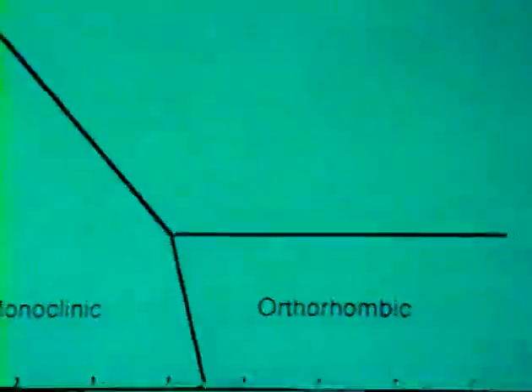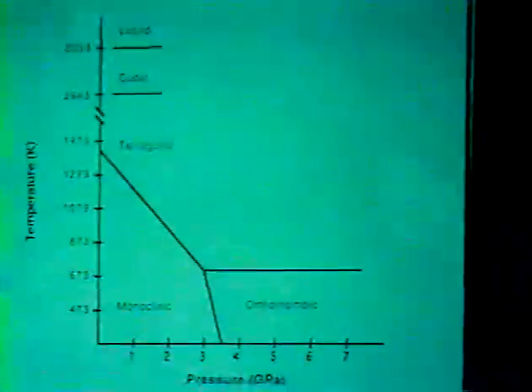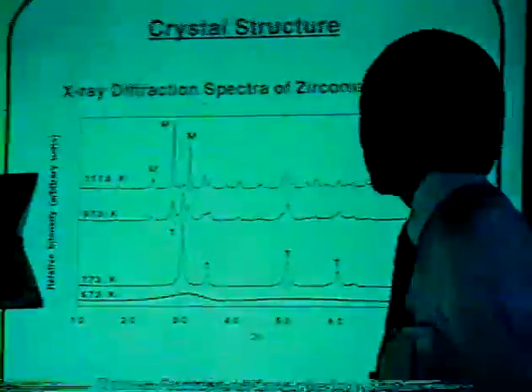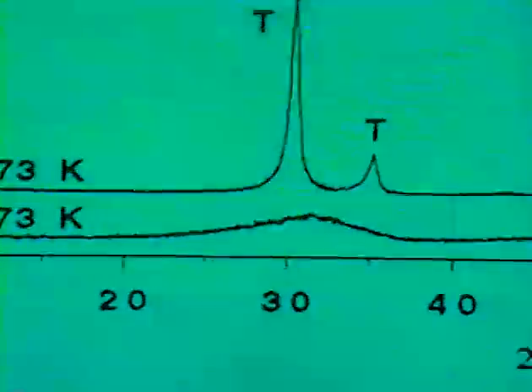What I want to do now is to shift gear a little bit and show you that gel time also affects the structural transformation of zirconia upon heat treatment. To set the stage for that, I would like to remind you of the phase diagram of zirconia taken from the literature, shown here. Now, if you look at ambient pressure thermodynamic data, zirconia exists in the monoclinic form. Upon heat treatment to about 1400 Kelvin, it will convert from the monoclinic form to the tetragonal form, and then finally from the tetragonal form to the cubic form before zirconia melts.